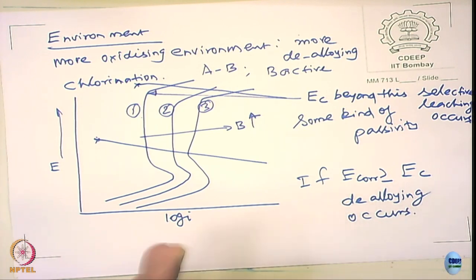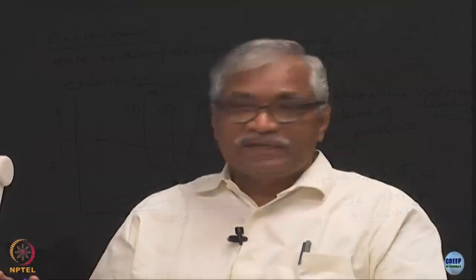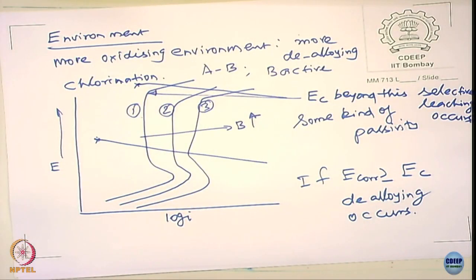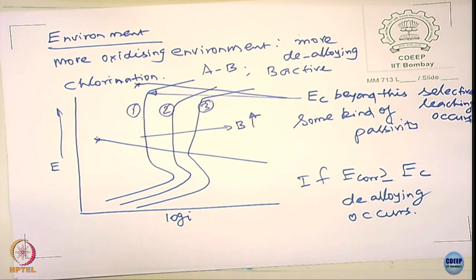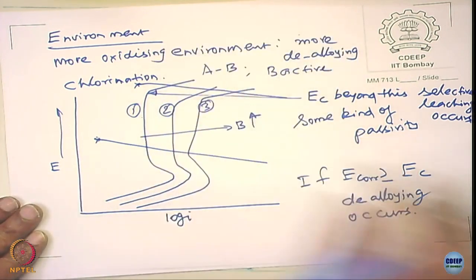It is not pitting here. You do not see a pit in this case. That is why in a copper zinc system and copper nickel system, you do not get a pit at all. If you observe the surface here, you will see the surface is enriched with copper, because zinc is just getting out of it. Similarly, in copper nickel, nickel comes out of solution. In fact, if you carry out a polarization on a copper nickel system, the solution color will turn green. Why? Because more nickel is being dissolved. So, you see a nice green coloration at this particular potential. You may see nickel also here, but the amount of coloration is very small. That is where you can show that nickel is preferentially dissolving at these potentials. Hope this point is clear to you.